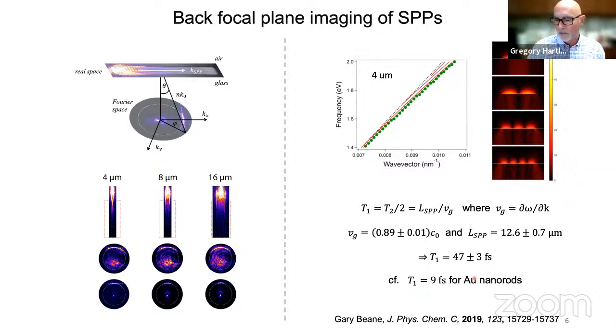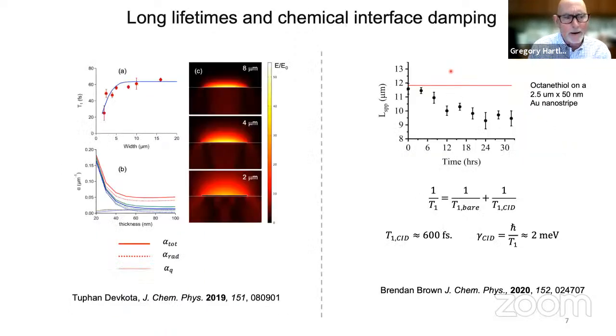So if you think about lifetime for the localized plasmon resonances in nanostructures, they're much shorter. So these modes, at least the leaky mode, can have much longer lifetimes. All right, so that's interesting. Maybe that would be useful for measuring things. And so this is now a plot of these lifetime measurements for a bunch of nanostripes with different widths. So the red points up here are the experimental measurements, and the blue line is a calculation, again from COMSOL, of what the lifetime should be. So we get a pretty good match between the experiments and the calculations, which is nice.